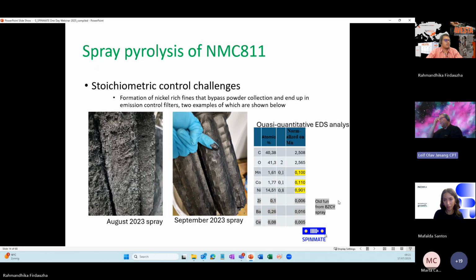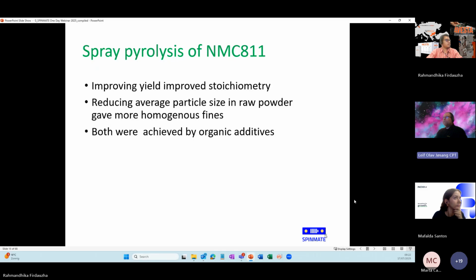So we've done EDS analysis at NTNU. It's not extremely reliable when you do it on a small sample of powder. I've stripped away the aluminium here, for example, due to the sample holder. But we see that there is more nickel here than there should have been. And that's the stuff that's missing from the cathode material that we actually collected. Yeah, I think we can move on.